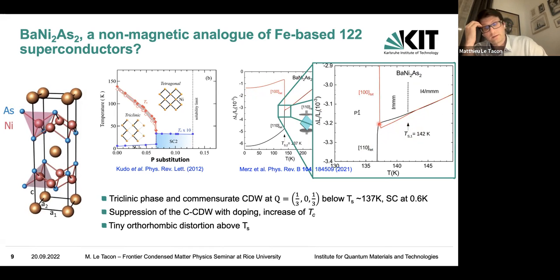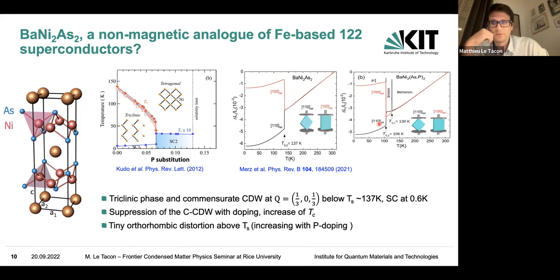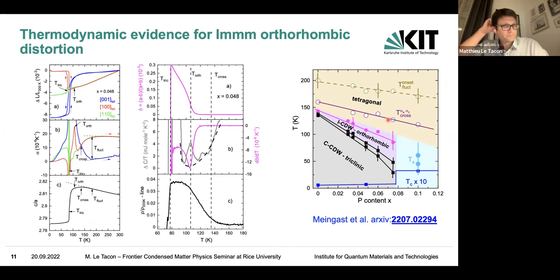And of course, it's a very small effect on the parent compound, but if you dope the material with a bit of phosphorus, I think it becomes really more obvious. This looks really second order now, and the amplitude increases a bit with that doping. Well, there's been further work on that, and I'm not going to detail that, but this was recently put by Christoph on the archive. And so we carried out a more systematic thermodynamic study of the phosphorus-doped system. Now this is for a compound which is close to 5%. So you see in the thermal expansion a lot of things going on, but in particular, if you look at the thermal expansion along the 100 direction, you see a clear peak here, which is due to the orthorhombic distortion.